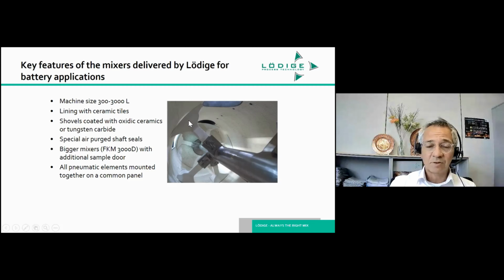The mixing elements that you see here, the plowshare tools, and the shafts are covered with either oxide ceramic or with tungsten carbide coating. Battery masses are toxic, so the issue of containment is a very big topic, and hence we have air purge seals, which help contain material inside the machine from the seal area. Likewise, the machine is dust tight with static gaskets fitted on each opening. For larger machines, you have sampling doors, and for ease of operation and practicality, all pneumatic elements are put onto a common panel.